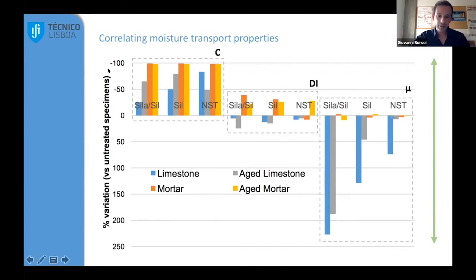So basically, if we look generally at the application of the hydrophobic product, we can see that there is a reduction of the capillary absorption, and that is what we are looking for actually. So those are positive properties. Then the second one, which is the drying index, we can see there is a differential behavior among the limestone and the mortar. And we can see that this balance should be respected. That is, the drying time should not be modified, because if you're looking for a very compatible material, you need something that is not affecting completely the drying phase, the drying index.